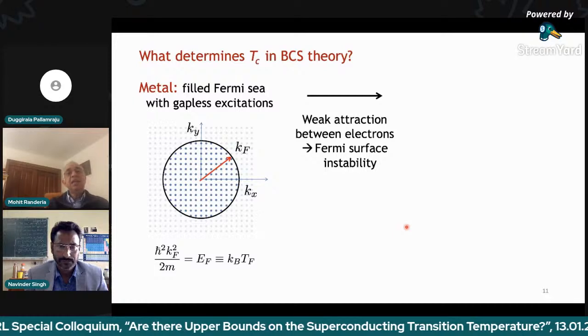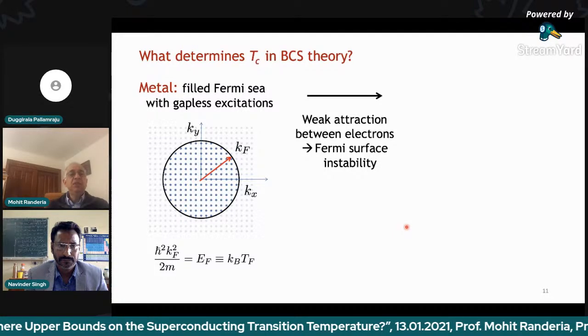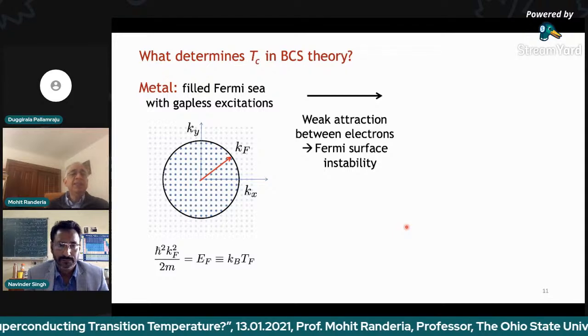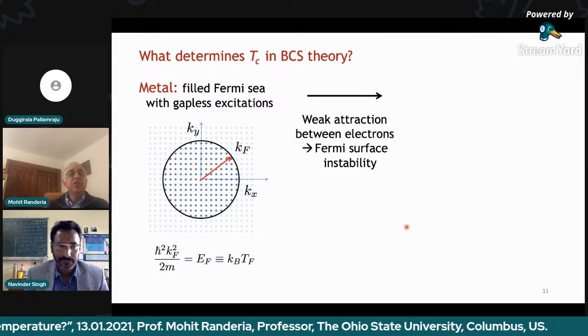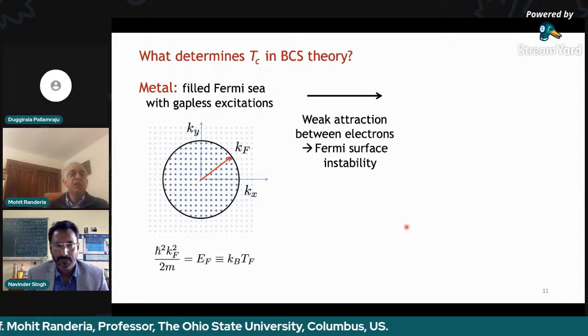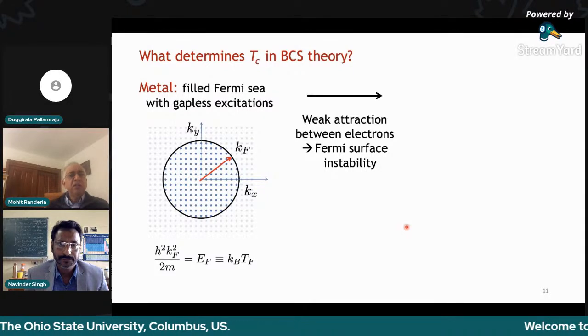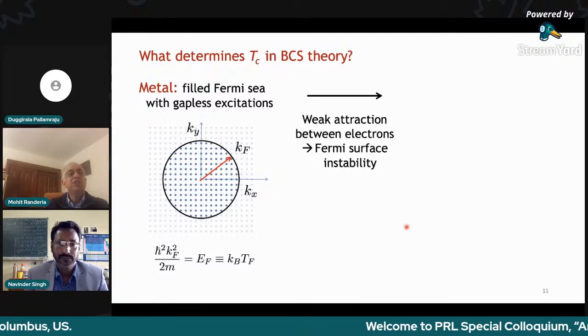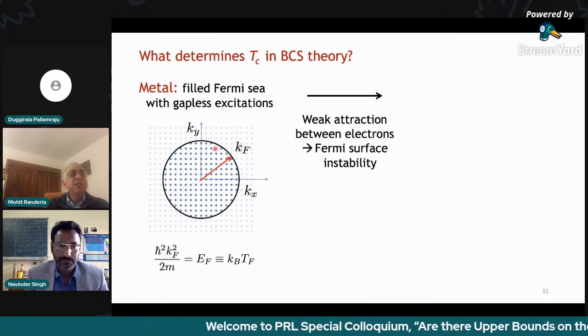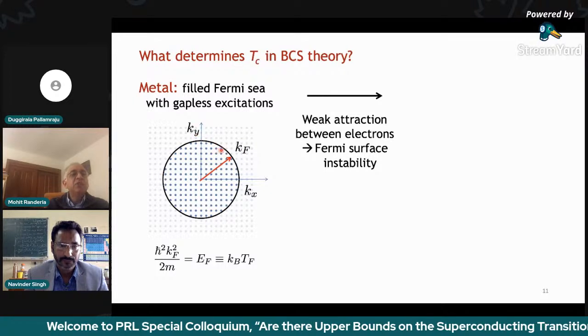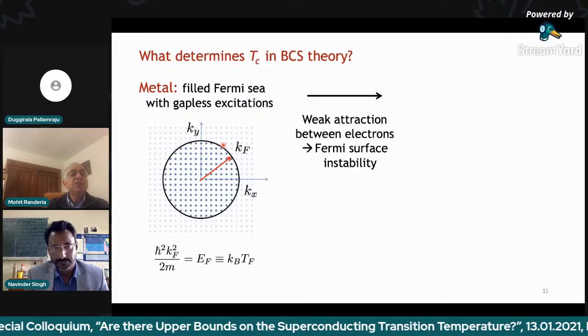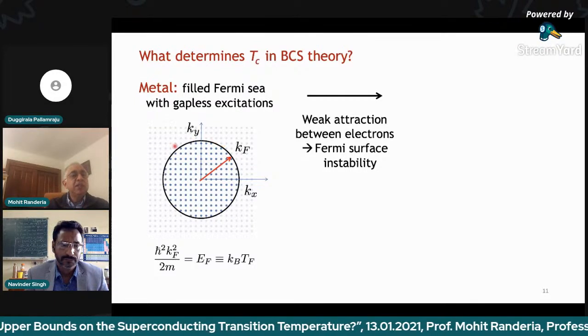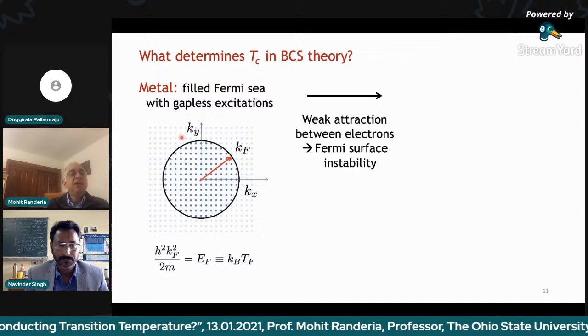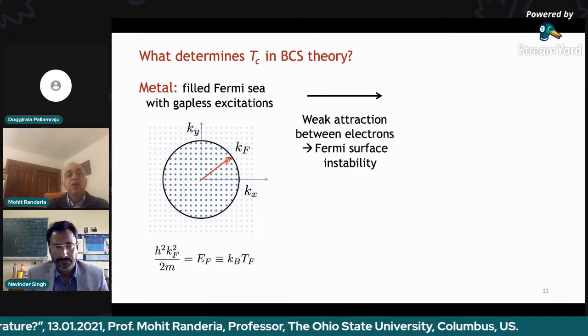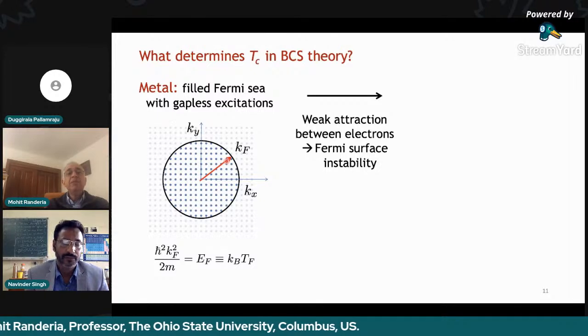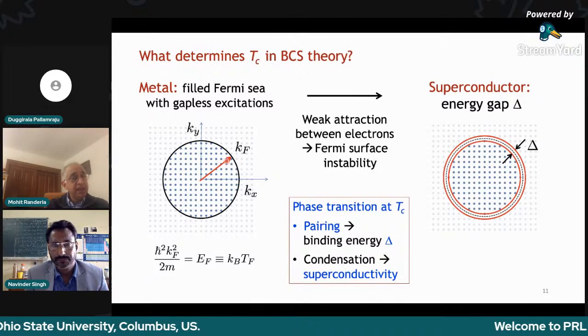And now what BCS said was that if you have a weak attraction between the electrons, and in the original BCS theory, they were thinking that the attraction would come from the interaction of the electrons with the lattice, or electron-phonon interactions. But the origin of the attraction is not so important. Of whatever origin, if there is a weak attraction, then this Fermi surface, which is a locus of gapless excitations, because you can take a fermion from inside and put it just outside the Fermi surface with very low energies, so there are lots of low energy excitations living all along the surface of radius kF, that becomes unstable, because what happens is that this weak attraction leads to pairing, okay?